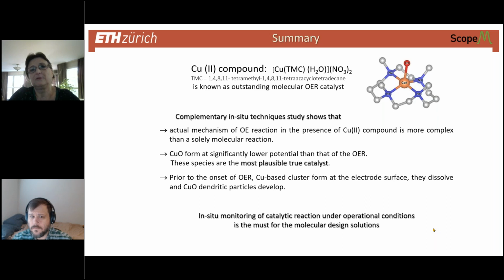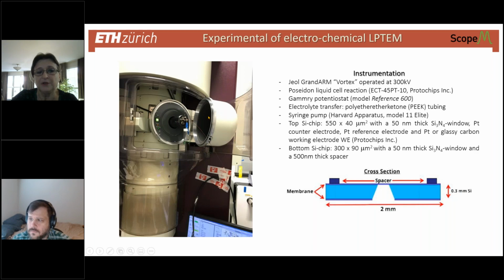That's why we had to revert to TEM, and we studied and selected the parameters. We found our parameters of illumination, of current, and everything, to be safe, not to change the pH value of the electrolyte, of the soup where the whole thing is cooking. And then we were sure we were the closest to the natural reaction path. STEM was no go, unfortunately, in this case. We used a 300 kV machine, a JEOL GrandARM machine, which was quite advantageous, of course, for transmitting through this whole thick sandwich. But maybe it gave us too many electrons in a very small probe. And that was not the way.